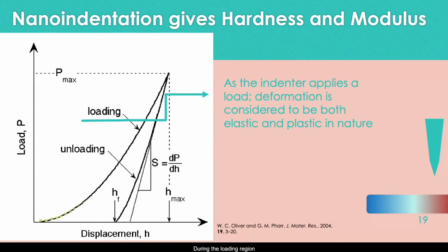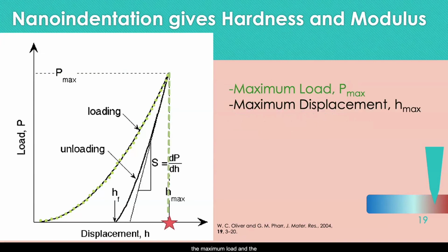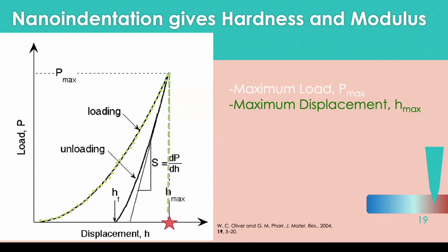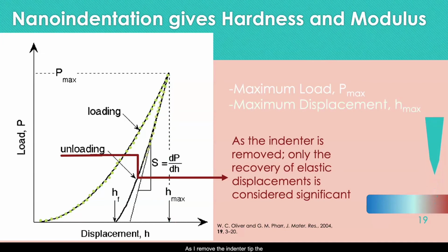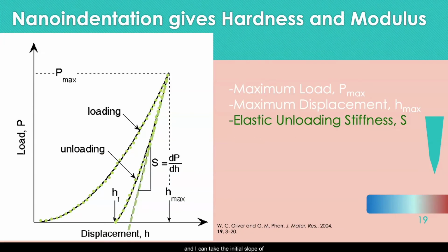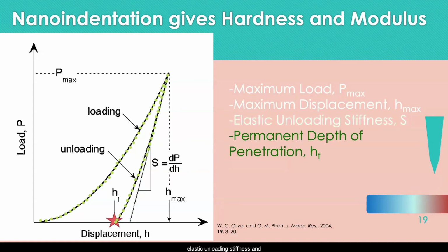And during the loading region, deformation is considered to be both elastic and plastic in nature, meaning that the shape of this curve is rather complicated. But I can look at the maximum load and the maximum displacement at that load. As I remove the indenter tip, the tip is unloaded, only the recovery of elastic displacements is considered significant, since only the elastic displacements are reversible. So the shape of this curve is maybe a little bit simpler, and I can take the initial slope of this curve and call that the elastic unloading stiffness, and also look at the permanent depth of the indent that's left behind after the indenter is fully removed.